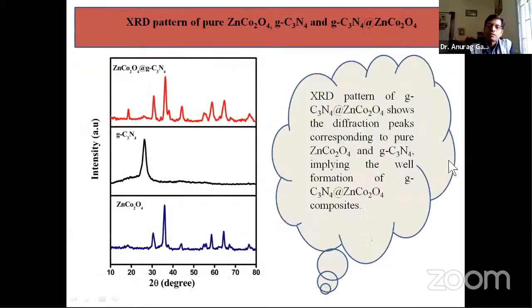So firstly, naturally, if you make any material, you have to check whether your material is being formed in the pure phase or not. That can be done through XRD analysis. This is XRD for ZnCo2O4, this is graphitic carbon nitride, and this is for the composite. In the composite, we are getting all these peaks corresponding to the ZnCo2O4 as well as the graphitic carbon nitride. Only then you could say it's a composite, because both materials are present with their phases. Otherwise, if you are getting some new peaks, it means something new has formed. So the composite has been prepared first, and then you confirm through this XRD analysis.